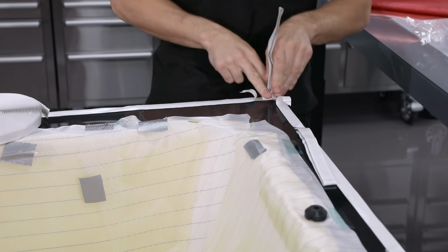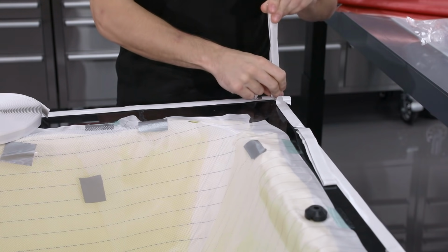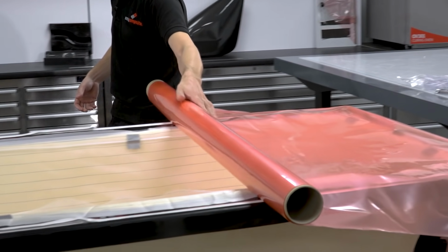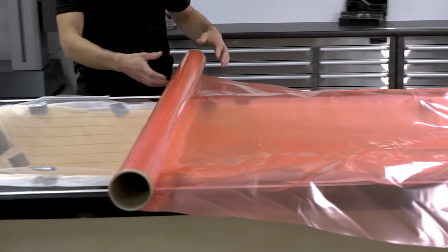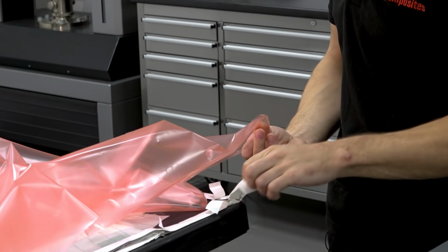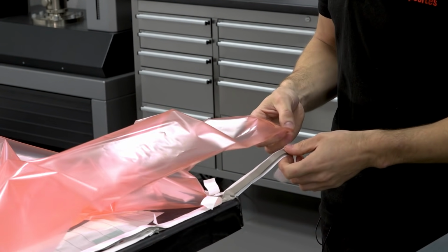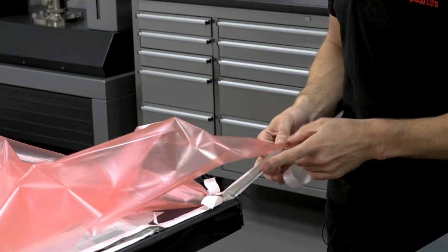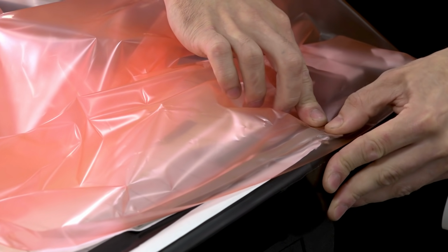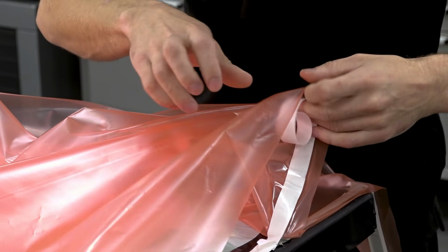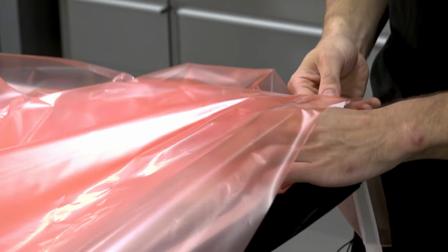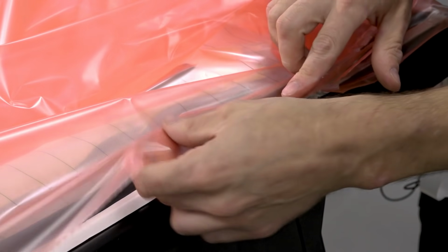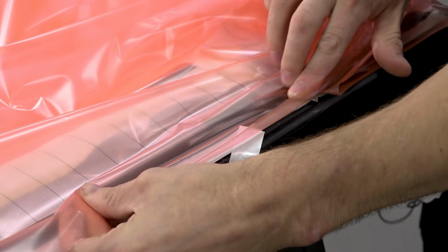With the pleats in place, we can now seal the vacuum bag to the mould. Resin infusion is completely merciless to the inexperienced when it comes to vacuum bagging. Even the smallest leak can cause a problem in the part, and so a slow and methodical approach is essential. General industrial hygiene and neat work really pay off here. I pay full attention to every millimetre of the seal as I'm applying the bag. It's much quicker to reduce the risk of a crease or a stray fibre when you're applying the bag than trying to find a leak later on.